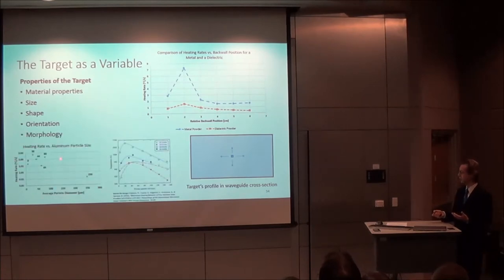The morphology is significant because as you change, for instance, the particle size of the metal, it'll heat more or less, and this correlates to some work that was done in the literature where we can see there's an optimal particle size for stainless steel powders, and this is illustrated by the data I took using aluminum powders.